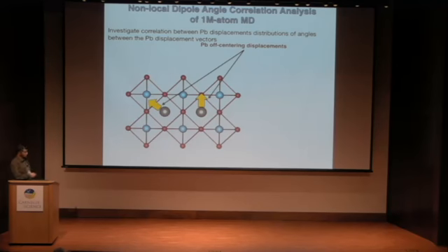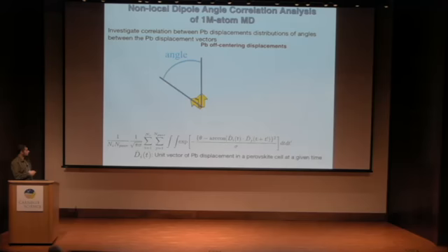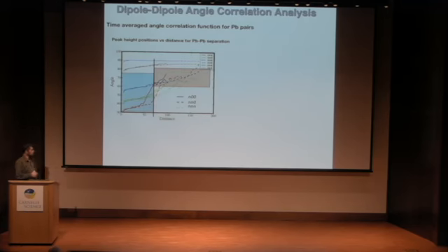So one over here, and we look at their angle. Okay, so the angular function, how much is the displacement correlated, which we can use this angle to measure. And what we found was something pretty interesting, as we look at the dependence of this angle with distance, in angstroms, and 90 degrees means that there is no order, because this is taken as the arc cosine of 0, and arc cosine of 0 is 90.